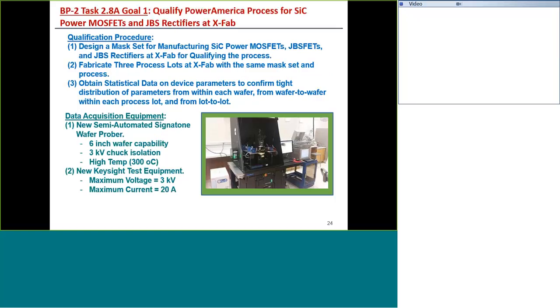So our qualification procedure, so I'm turning back to goal 1, which is to qualify the process. Our qualification procedure was to design and make a mask set for manufacturing silicon carbide power MOSFETs, so we're qualifying those. We're also qualifying a process for JBS FETs, and then we're qualifying a process for JBS rectifiers. Then we wanted to run at least 3 lots. I should say we decided to run 3 lots with the same mask set and process, which are staggered, so that we can then compare the performance between these lots, confirm that we have very good parametric distribution within each lot from wafer to wafer, and then from lot to lot.